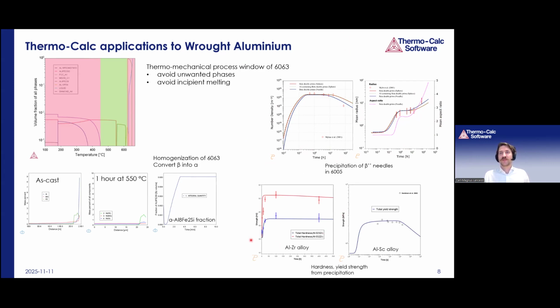Now these are examples on binary alloys, aluminum zirconium and aluminum scandium. So here we are simulating precipitation of aluminum zirconium precipitates and calculating the Vickers hardness for two different chemistries. And here on the right, this is one of our oldest examples of the yield strength model, where we are simulating the strengthening effect of the Al3Sc particles as a function of time.